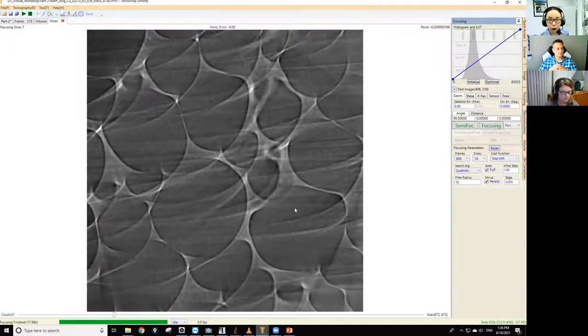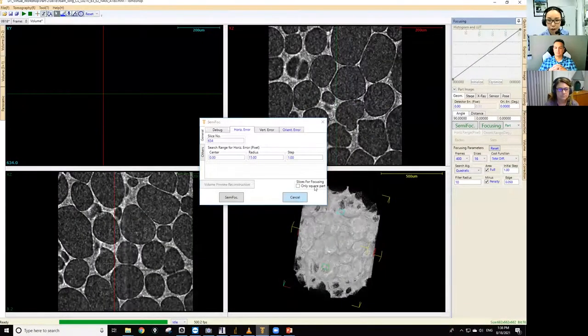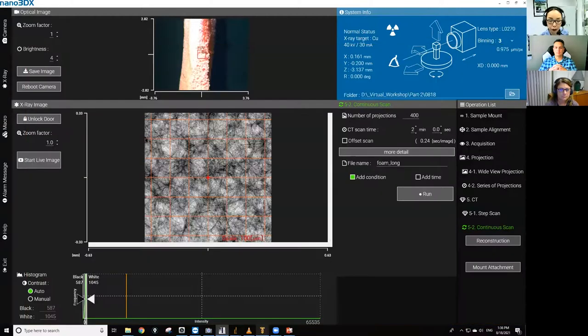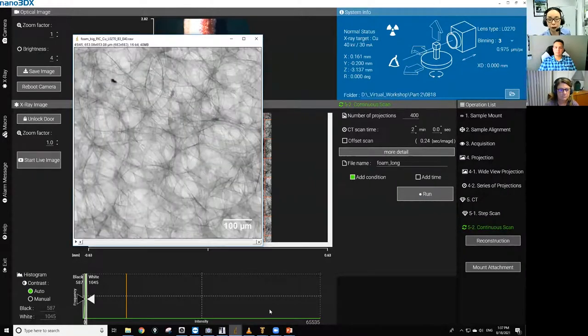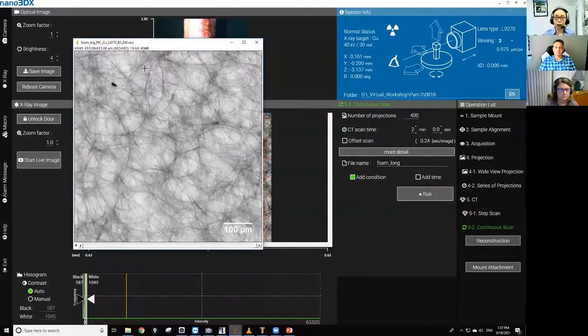Now, I'm going to show you something else. Let's say that you're planning to do a 10, 20 hour scan. You don't want to spend 20 hours and hope for the best, and come in next morning and realize your sample was moving. That's probably not a good strategy. So if you're planning to do a long scan, I would recommend you take a look at the projection like this one. This is just a 2D projection, not 3D CT. Collect the projection every minute or so for 45 or 60 minutes to see if the sample is moving, or to see how long it takes for the sample to settle and stop moving.